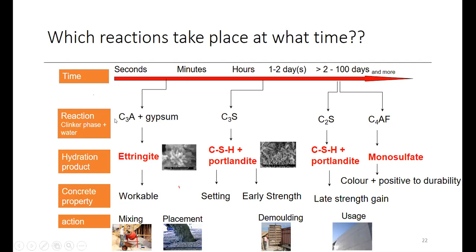We'll see the reaction phases when we use cement, when we mix it with water, what reactions could happen, and what would happen with time. So in the initial stage, C3A will react with gypsum, meaning SO3, and it will form ettringite. Just focus on that ettringite.